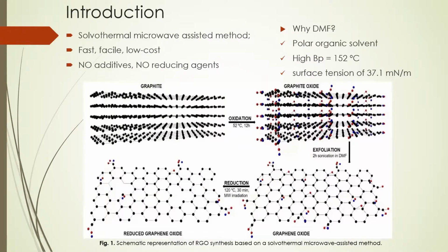Reduced graphene oxide is a two-dimensional carbon-based material with mechanical, optoelectronic or conductive properties very similar to those of pristine graphene. This is due to RGO's heterogeneous structure composed of a pristine graphene-like basal plane with few topological defects and highly oxidized regions. Although RGO can be rapidly synthesized from graphene oxide, shortly GO, in aqueous solutions, there is still a great challenge in synthesizing RGO in organic solvents.